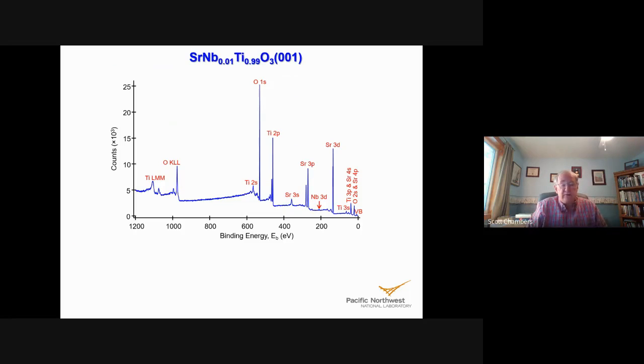Okay, so here's a typical spectrum, and if you've done any XPS, this looks very familiar. What you see is different elements, and different orbitals giving peaks at different energies, and this is for niobium-doped strontium titanate single crystal, and it's clean, the surface is clean. Any given element on the periodic chart will have a characteristic set of photoemission peaks for its different orbital energies, and it's like a fingerprint, and that's very useful, obviously. But if we want to go further and know more than just what elements are there, then we need to understand the line shapes.